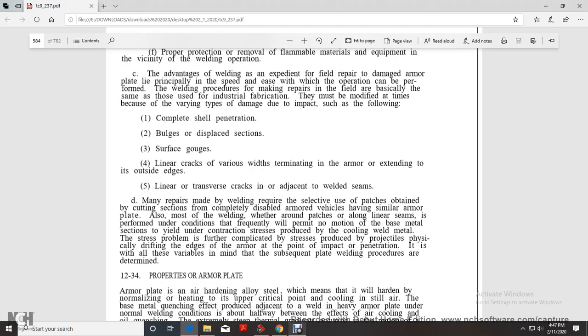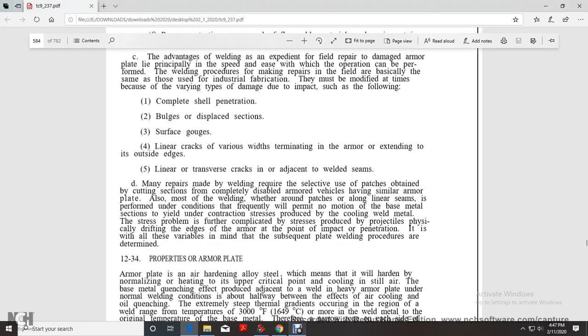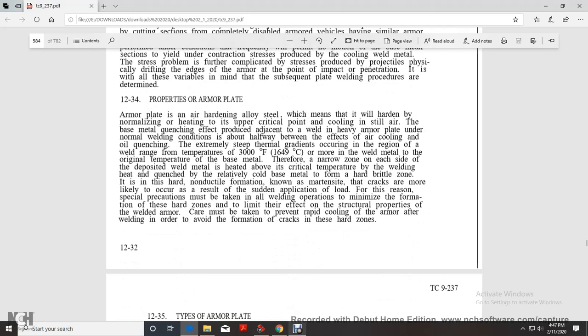Many repairs of the welding require selective use of patches obtained by cutting sections from a completely disabled armor vehicle having similar armor plate, with the patch welded along the linear seam. Under these conditions, the welds frequently permit no motion of the base metal, and the section yields under the contraction stress produced by the cooling welded metal. This stress problem is further complicated by the stress produced by the projectile physically drifting the edge of the armor at the point of impact or penetration. With all variables in mind, the subsequent plate welding procedure is determined for the armor plate.